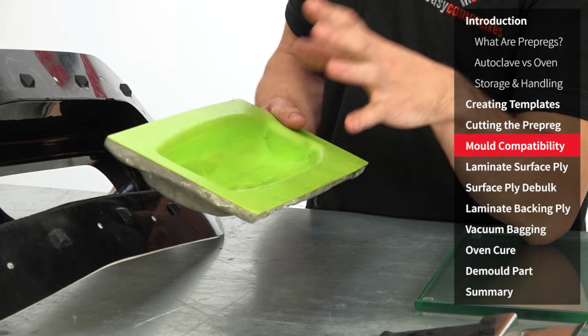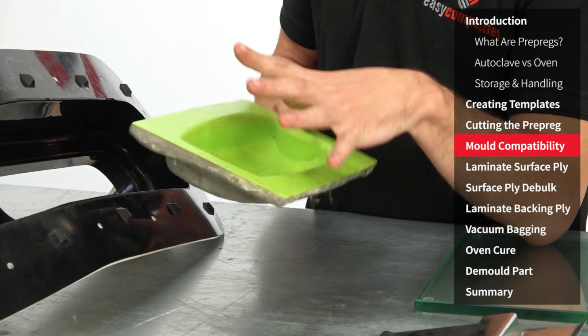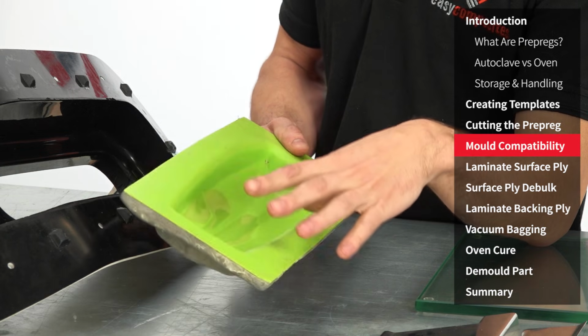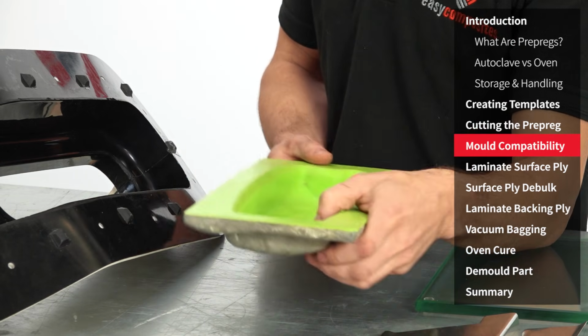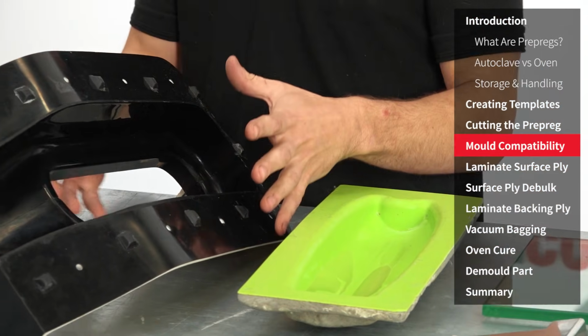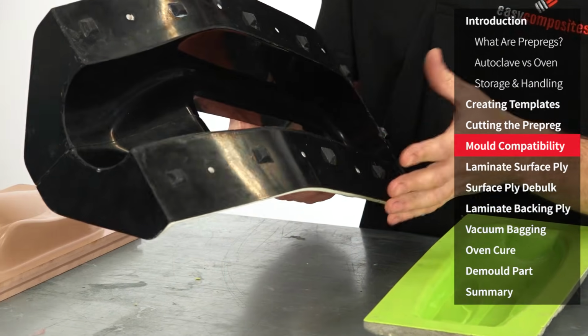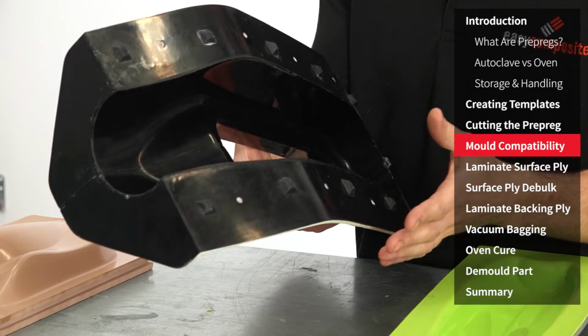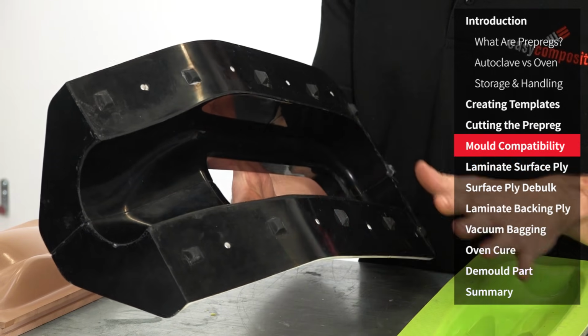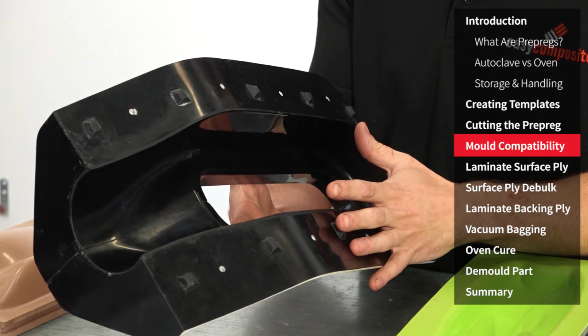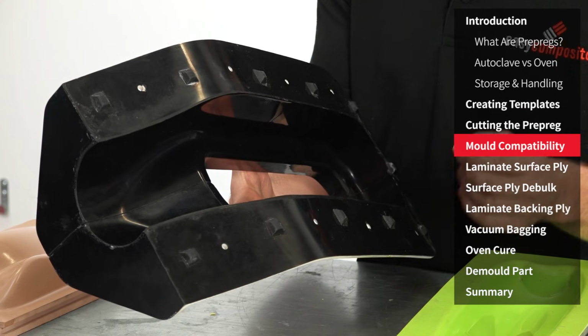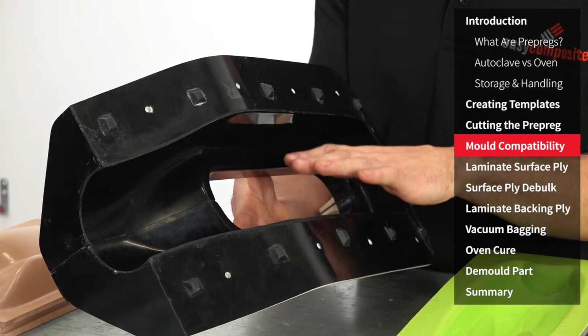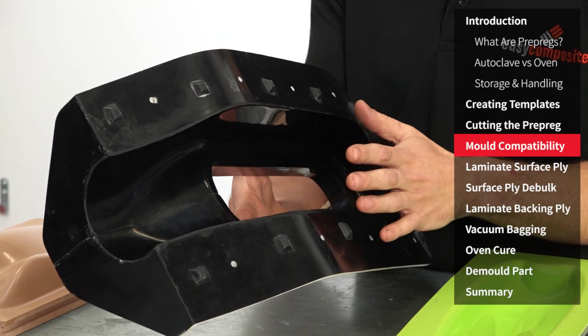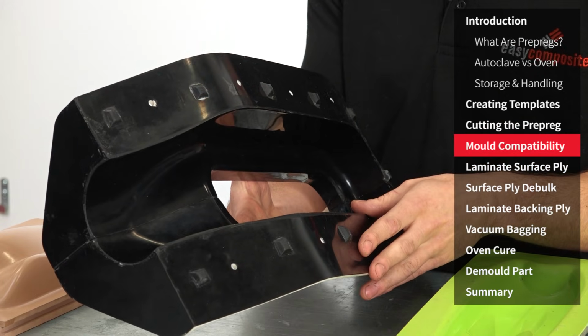This mould has been made using a standard epoxy tooling system, which means that it doesn't have a particularly high service temperature, so you'd be limited on the cure cycles that are available. So although it could be used, we don't recommend it. Another material which isn't ideal are vinyl ester tooling systems, such as our Unimold system. The reason for this is twofold. Firstly, again, it doesn't have a particularly high service temperature, so you're limited on your cure cycles, and you can encounter a compatibility issue between the mould surface and the pre-preg, leading to minor surface imperfections.